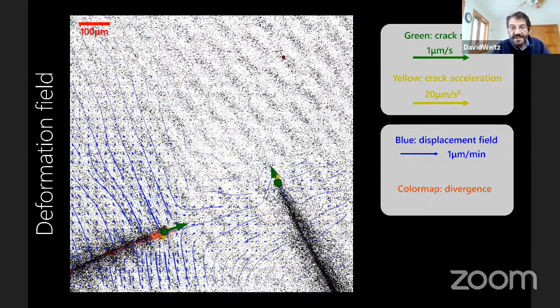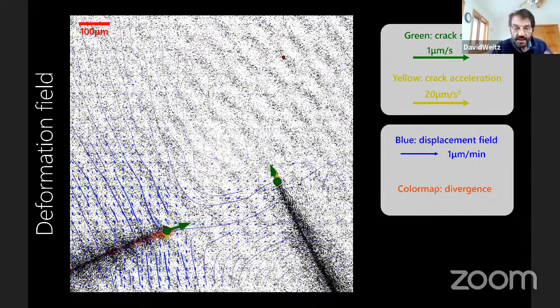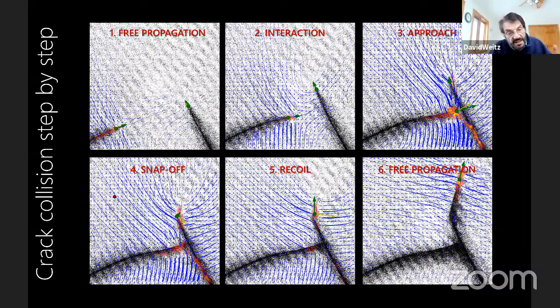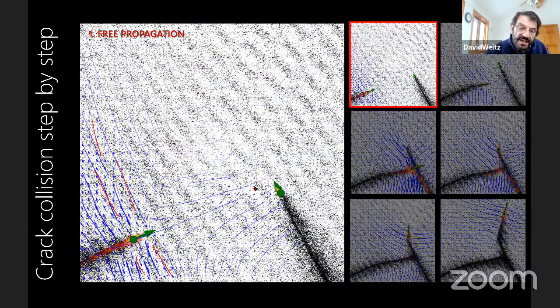So let me just show you the steps that occur in these interacting cracks. First, you have the propagation. This is occurring because you're driving the fluid in, and you can see the strain field. It's falling off quite far away, but there's strain all the way around because it's a solid. It doesn't look like a solid because it's relatively clear, but you can see that it's a solid because you can see the speckles and you can watch the way they move. As you come closer, again, the strain field now starts interacting. There's another strain field that's moving out in this direction from this crack and this direction from this crack, and you can see the way they interact.